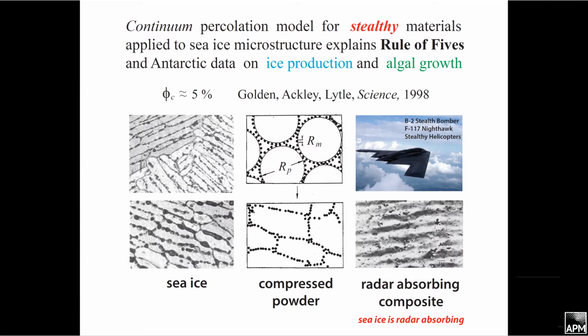And it turns out that it's extremely similar to the microstructure of so-called compressed powders, big polymer spheres and little conducting particles that are then squashed to form these compressed powder microstructures. But if these particles are highly conducting, then this is what is known as a radar-absorbing composite that was used in the development of stealthy aircraft to evade radar. And so we employed this continuum percolation theory that gives the percolation threshold for these kinds of materials, and we applied it to sea ice, and we're then able to predict the 5% and all kinds of data on ice production and algal growth and so on.